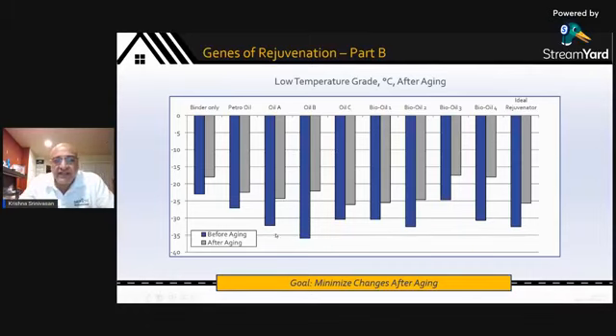And so right away you can see that this material, which was the most efficient on day one, shows very dramatic changes upon aging. And that was the whole driving force behind our rejuvenator development. Not only did we want a high level of performance, but we also wanted to minimize the change upon aging. As I mentioned to you, our goal is to provide a rejuvenator that not only satisfies your requirements today, but is stable over time, gives you performance of the roadway, and makes the whole pavement impervious to the fact that whether you've added high RAP, low RAP, no RAP, it really doesn't make a difference. That is our goal.